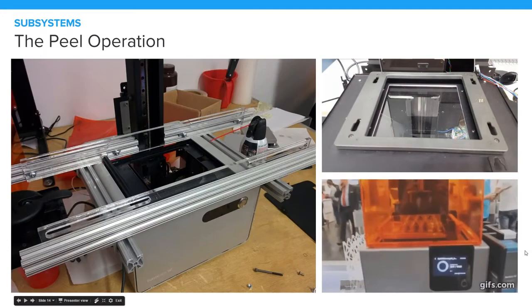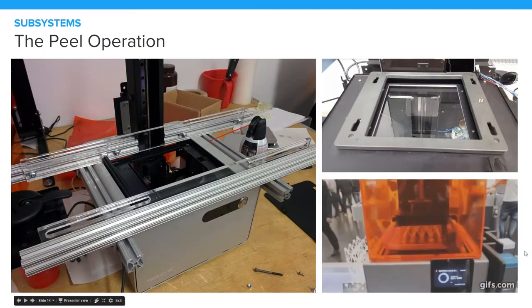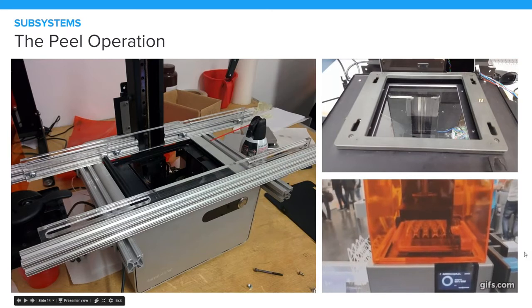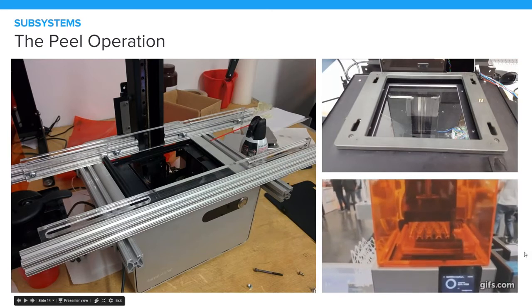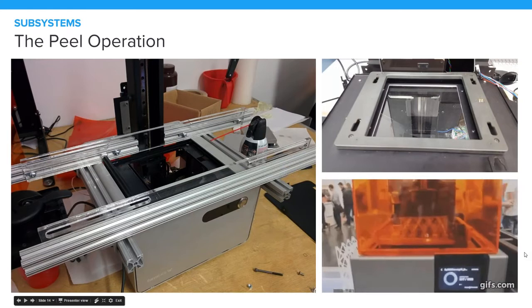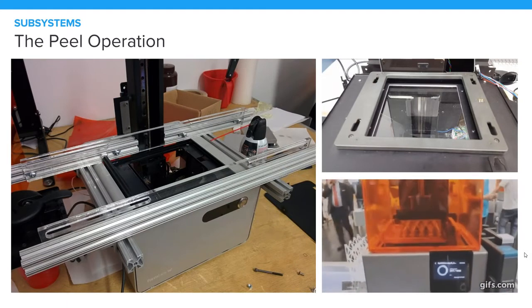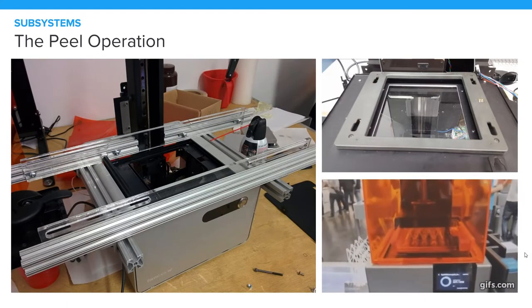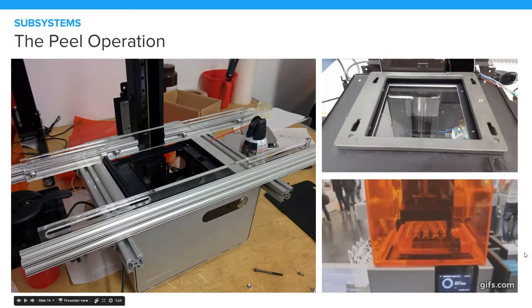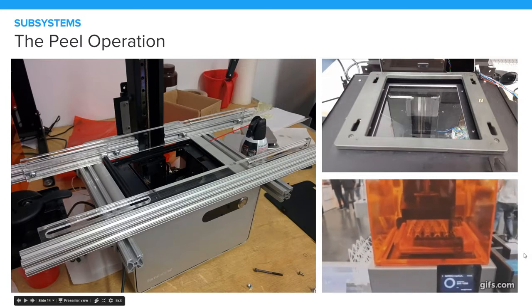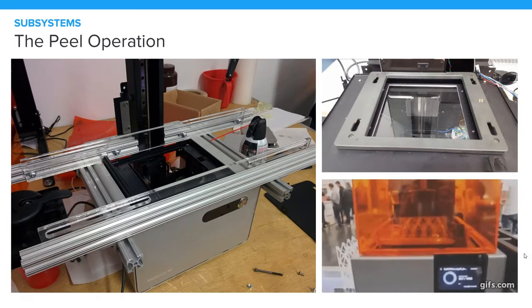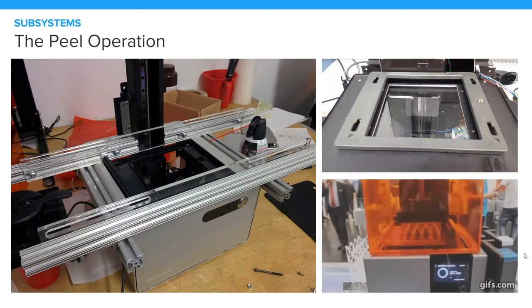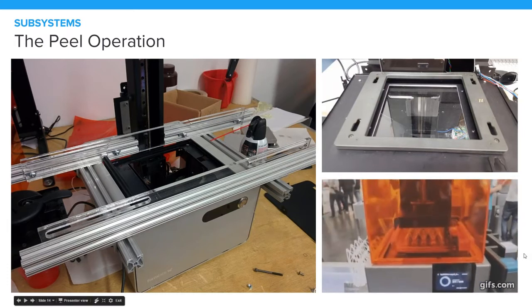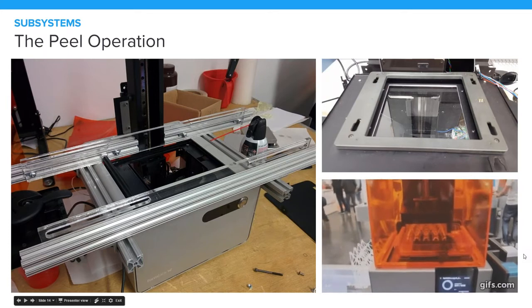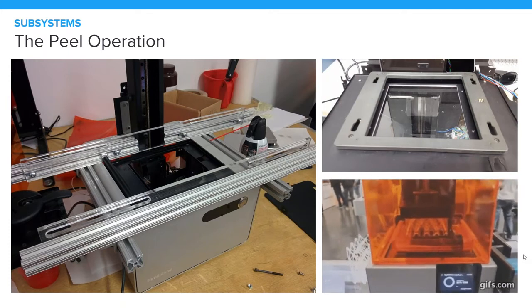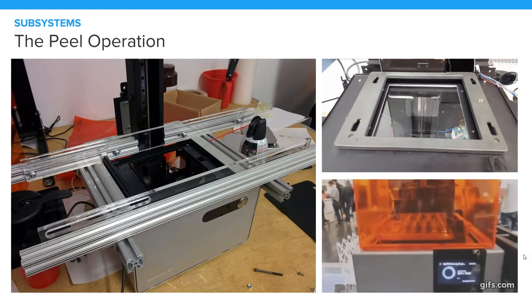So the peel operation is another critical component of any inverted SLA or DLP process, and it's one of the biggest areas that we look to improve on from the Form1 Plus. The peel operation basically is there to remove the freshly cured resin from the bottom of the tank. If you think about it this way, when your part is cured, it's cured to both the build platform and the bottom of the resin tank. So that sliding mechanism that's in the Form2, or the lever action that's in the Form1, is there to remove the part so that the build platform can raise up and the next layer can be printed.